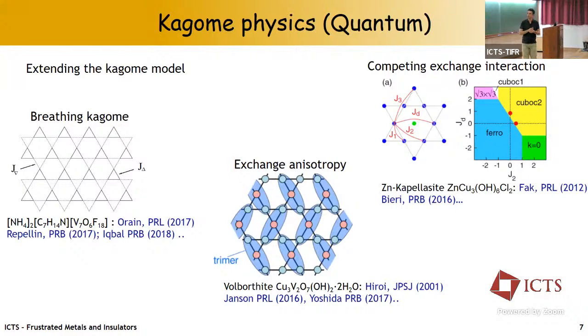So let me give you a few examples of distortions that we could imagine. There are harmless distortions, such as in this breathing Kagome, where you can think of allowing for two different sizes of the triangles. And this is actually realized in this material that we have been studying. Magnetism is from vanadium here, and it has triggered theoretical work. And it's actually very interesting. The Kagome physics seems to be very stable up to large breathing ratio.